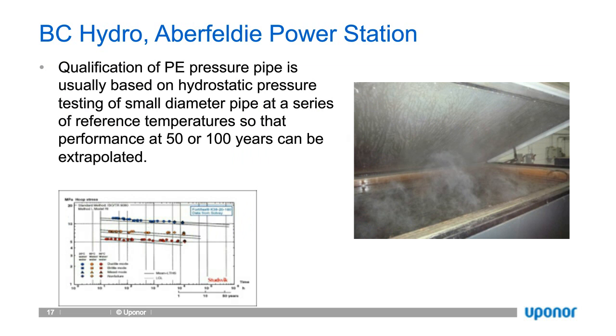I think it's useful to have a little bit of an understanding about how polyethylene pressure pipe and polyethylene resins are rated. A qualification of PE pressure pipe is usually based on hydrostatic pressure testing of small diameter pipes at a series of reference temperatures so that the performance at 50 or 100 years can be determined by extrapolation. Clearly, we don't want to be testing pipe for 50 or 100 years in order to know what its pressure rating is. And again, unlike steel, where the properties for long duration and short duration are the same, it varies with plastic materials.